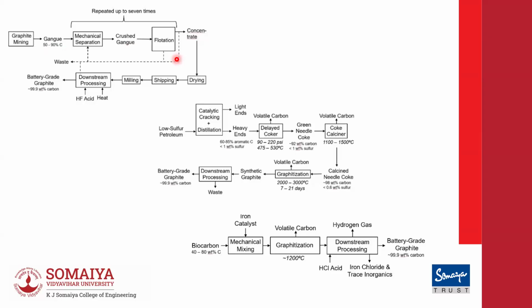So you need to separate the graphite powder by a flotation process. Then you have drying, sieving, milling, downstream process. So you do have energy coming into the picture. You do have other material coming into the picture, like your downstream processing requires hydrofluoric acid treatment. And then you get your battery graphite, which is around 99.9%. So from 50% to 99.9.